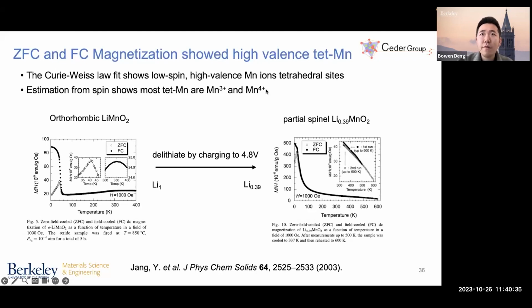By performing zero-field-cooled and field-cooled magnetization experiments on both the orthorhombic starting material and this partial spinel material, they obtained this magnetic susceptibility versus temperature plot. And by fitting to the Curie-Weiss law, what they found, surprisingly, is low spin and high valence manganese ions on the tetrahedral sites. In other words, they estimate that there are actually more tetrahedral manganese 3+ and 4+ ions than what has been proposed by John Reed, only manganese 2+ ions on the tetrahedral sites.